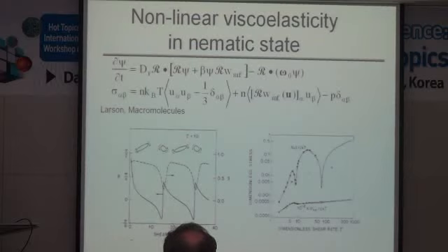Accordingly, the relationship between the stress and the shear rate becomes quite unusual. Shear stress is not a monotonically increasing function of the shear rate, and also the first normal stress difference changes sign from positive to negative in a certain shear rate region.